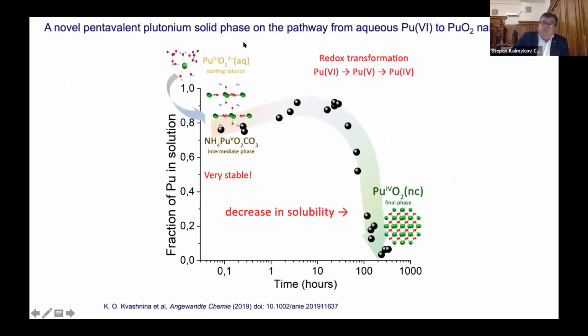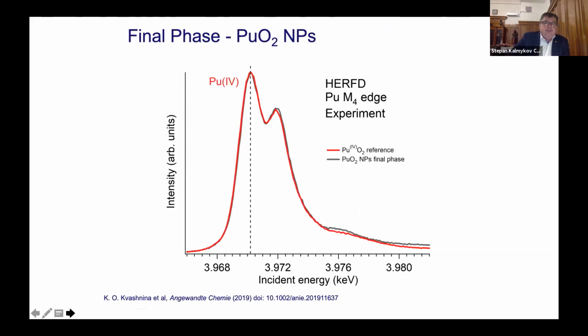So it looks like this: we start with hydrated plutonium-6 aqueous species, then there is an increase in solubility because of the redox transformation to plutonium-5. We have this intermediate phase, ammonium plutonium-5 carbonate, and then there is a slow decrease in solubility that is due to the relatively slow reduction of this intermediate phase to plutonium dioxide nanoparticles. So under steady state conditions, at the end of this process, we also have plutonium dioxide-like nanoparticles. They are also 2 nanometers in size, and they are also crystalline.